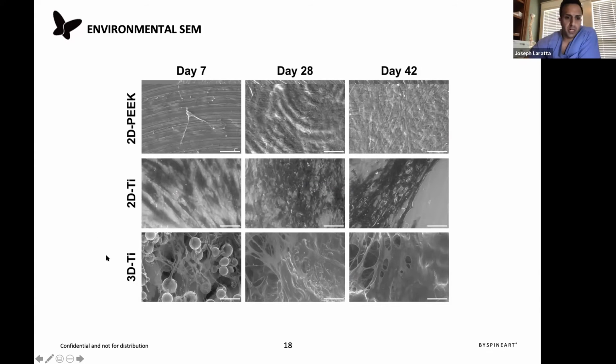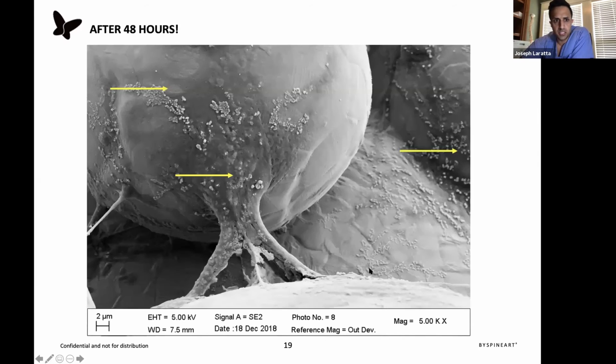And then when you look at three-dimensional titanium, and this is the TiLife technology, you can see early elongation of the cells at day 7. These are the cells, and you can see elongation of extracellular matrix. But at day 28 and day 42, the layer of cells that remains attached to the metal itself is so dense that it's really impossible to distinguish the cells themselves from the extracellular matrix that they deposited.